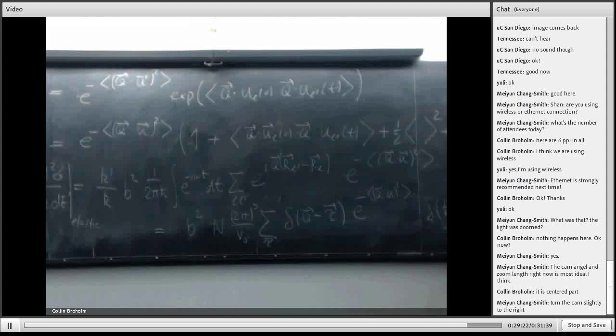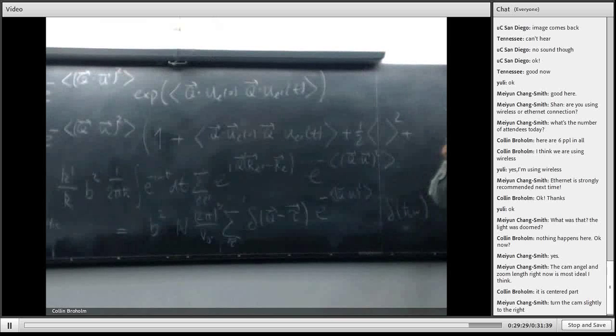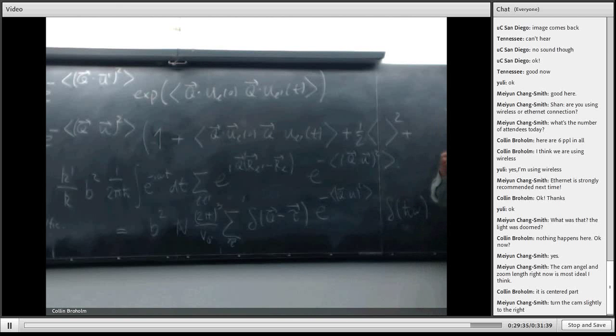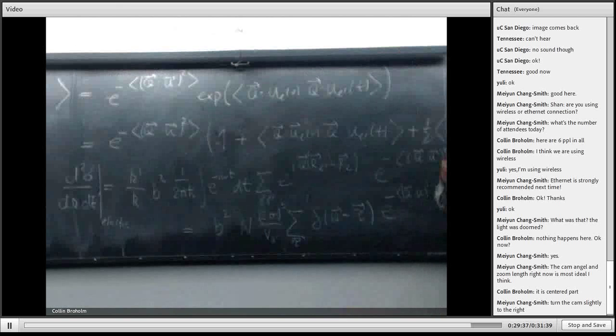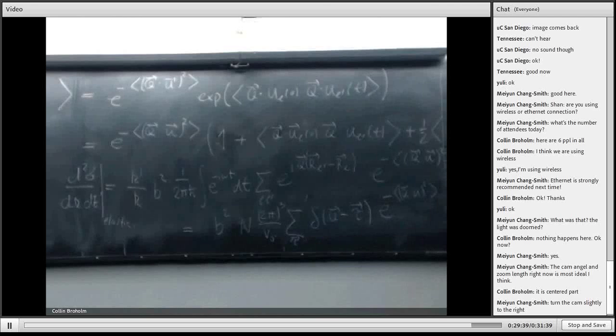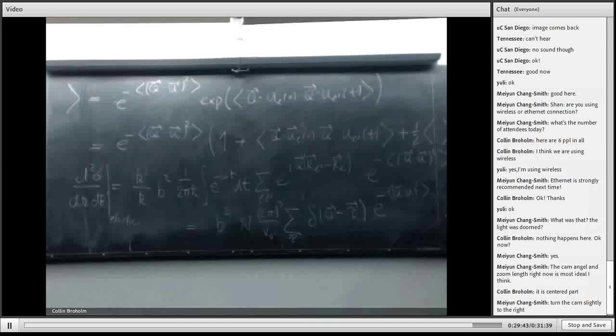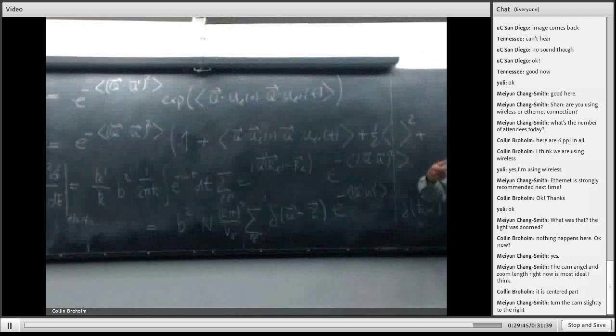So in a sense, what's happened is that instead of being really the Dirac delta function Fermi pseudo-potential, this has now been distributed somewhat in space as a result of the thermal motion and the quantum motion. So the quantum zero-point fluctuations will have such an effect too. They spread the apparent size of this interaction potential, and that causes the overall scattering intensity to decrease at higher and higher momentum transfer. So that was the appearance of that term.